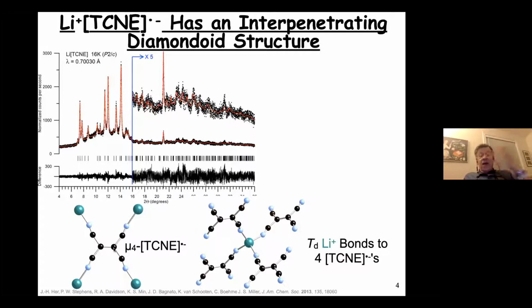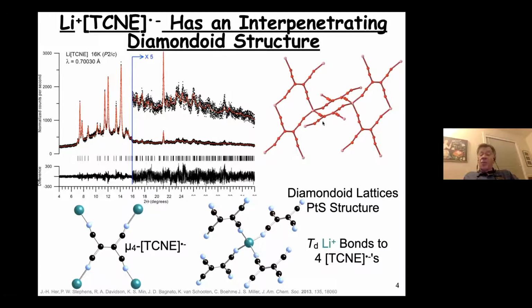TCNE radical anion is planar in the same plane of the 4 lithium ions. And this enables us to form this lattice, which is a diamondoid-like lattice with the platinum sulfide structure, where we have a tetrahedral lithium surrounded by 4 TCNE radical anions, and each TCNE radical anion is surrounded by 4 lithiums. There's a lot of open space in this structure.